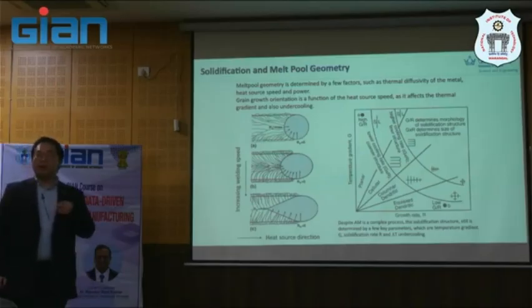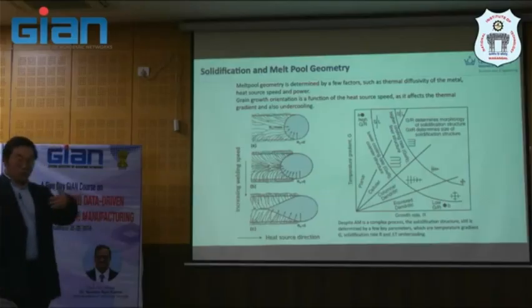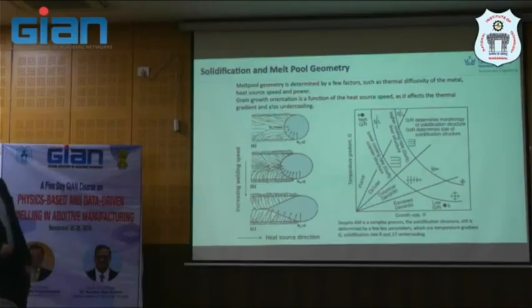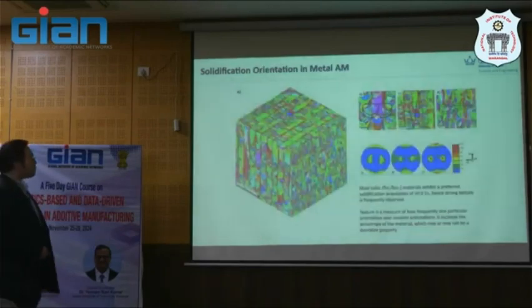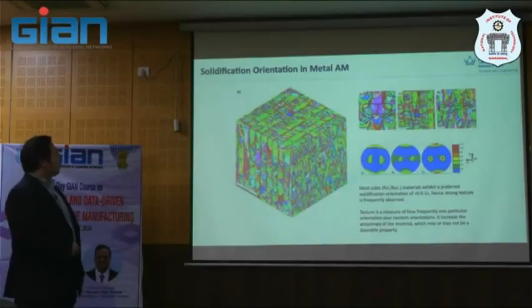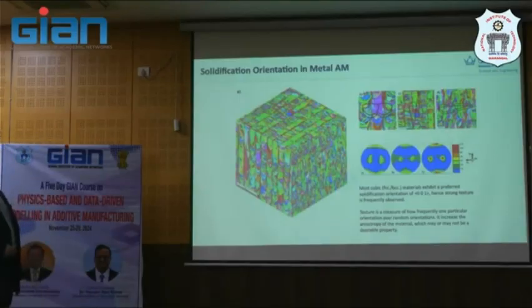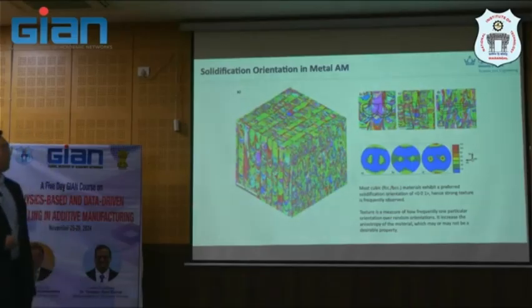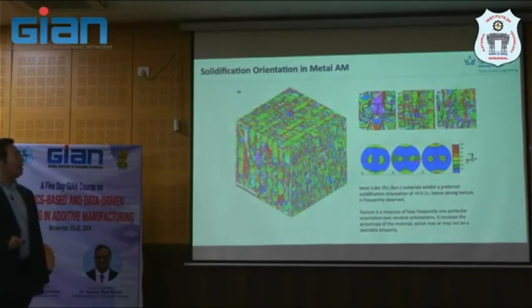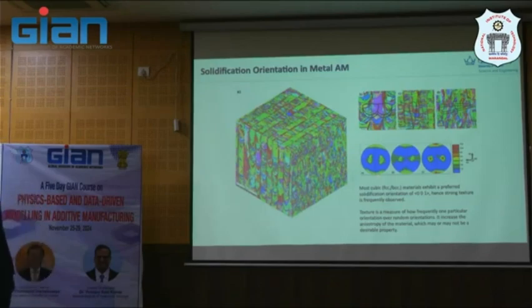It's not immediate. If you scan one track, you may see mostly cellular or planar structure. So this is the work, this is not a 3D map, but anyway, that's represented in 3D, but looking at a different section that you have in this way, and this way. And then you see the microstructure at 3 different locations are different, evidenced by the statistical approach here, a whole figure, which is a collection of grain IDs that you map onto this stereographic orientation.